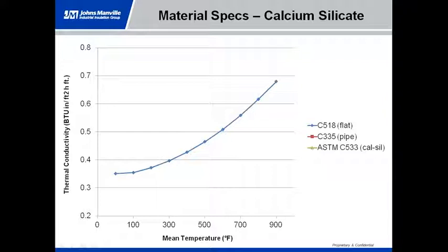We take a measurement. We increase the mean temperature to 200 degrees. Wait for it to come to equilibrium. We take another measurement. We do that until we get to, in this example, up to 900 degrees. Kind of another giveaway that this is flat testing is we can go up to 900 degrees and still get a decent data point. Now, when we do the round testing, again, we have that mean temperature that's much harder to accommodate because we have to get our pipe temperature so hot. So if you look at the data here between 100 and 200 degrees, very similar, probably within the uncertainties of the test method, so there's some overlap there.